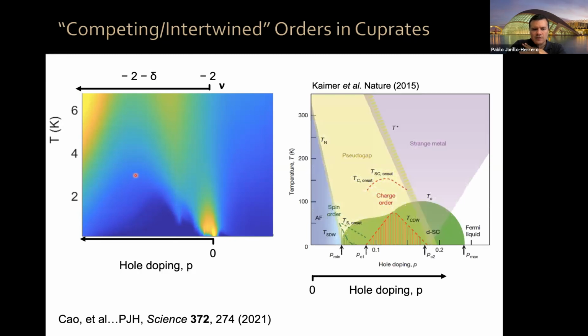Now, the moment I saw this, it reminded me again of these types of pictures. This is 0 doping, lattice, so filling factor 1 if you want, and then as you add holes, which in the cuprates they usually show in this direction, you have this type of behavior with a double hump dome. So again, it was quite reminiscent, so we tried to look at it a bit more.